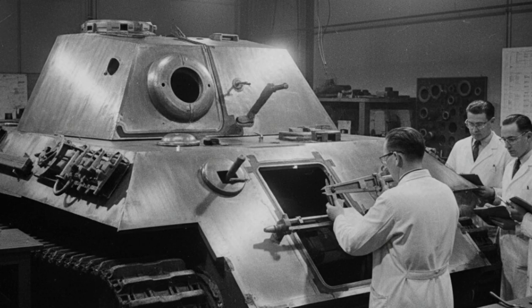British armor analysts also noted the efficiency of the gun system. Using 7.5 cm PzGr 39/42 ammunition, the Panther penetrated a 4.7-inch, 120 mm, British homogeneous plate at 1,000 yards, an impressive figure that surpassed the 17-pounder's APC at the same range. Yet the rate of fire, only 6 to 7 rounds per minute, was slower than Allied standards.